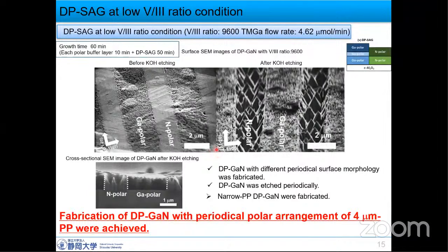On this slide, I'm talking about DP SAG at low V/III ratio condition. We fabricated DP GaN grown with V/III ratio 9600. Following the surface SEM image before KOH etching, DP GaN with different periodic surface morphology was fabricated. Following the surface SEM image after KOH etching, DP GaN was etched periodically.